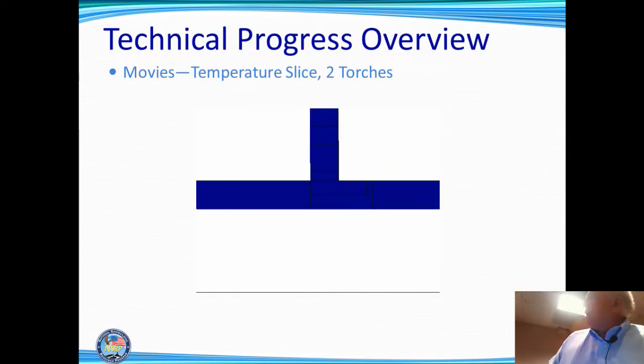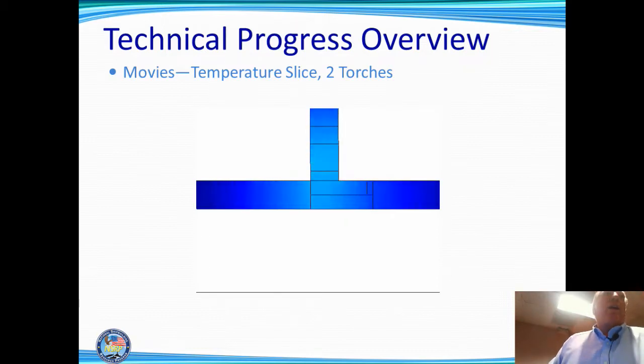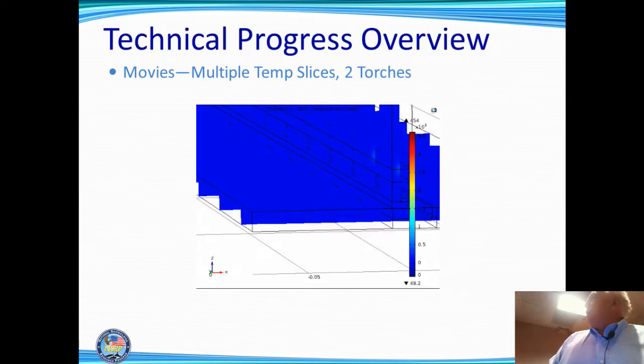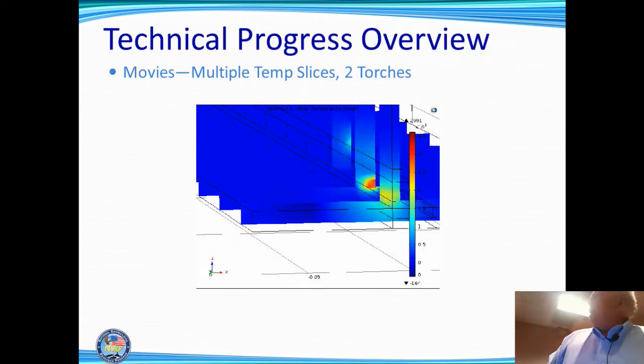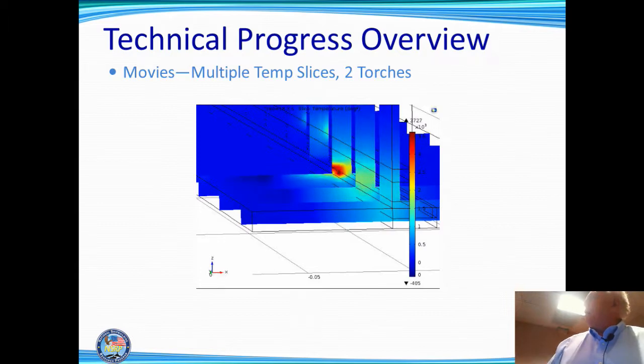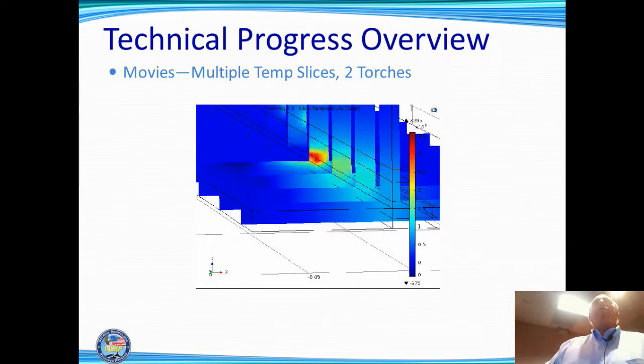You see the induction heat at the top, and then the two arcs, one on each side. And we've got that same one in cross section here as it sort of runs down the plate. So there's a whole series of cross sections there, and you'll see the induction heating up above, and then the arc on the right and the arc on the left as we go through each one of those cross sections as we're moving down the plate. And we used this to figure out exactly where we should put the induction heat to get the heat distribution so that we would essentially zero out the amount of distortion we got.